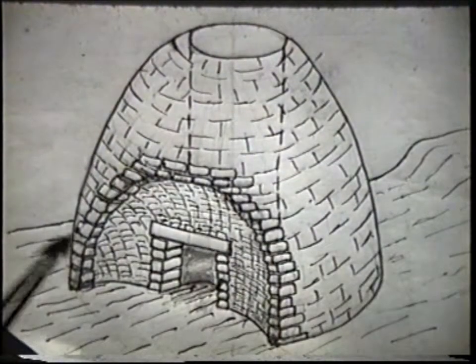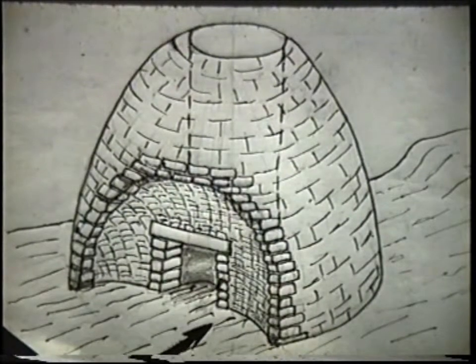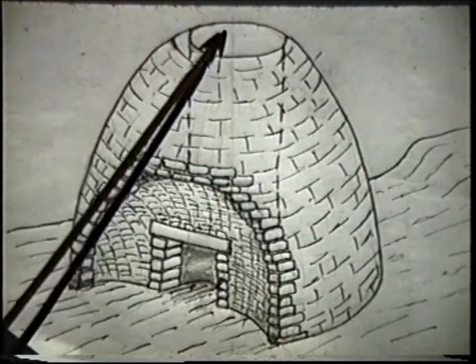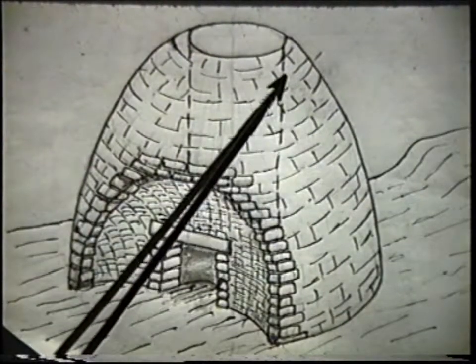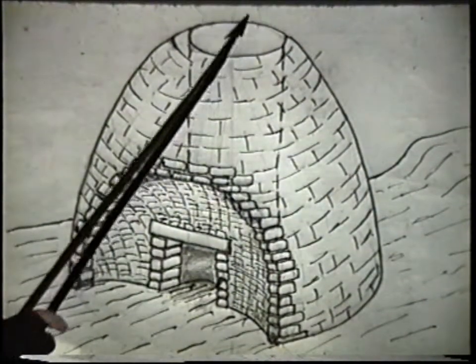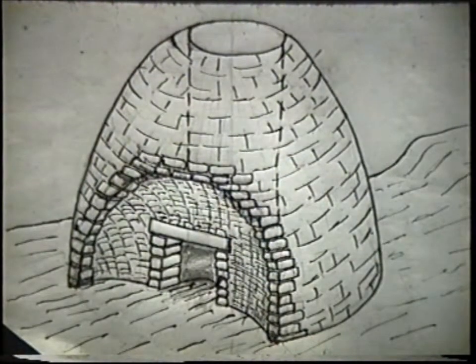This was my fanciful interpretation of what a complete lime kiln would have looked like, with the firebox down in the bottom and the centre flue. You had to fill it, so usually these were built against a hillside so that you could fill it from the hillside. If there was no hillside, they very often had steps up so that the lime burner could carry the limestone and fuel up on his back and tip it into the top. The fire was lit and then it was covered over with turf and just allowed to burn quietly for perhaps a week in order to thoroughly bake the limestone without destroying it by burning.